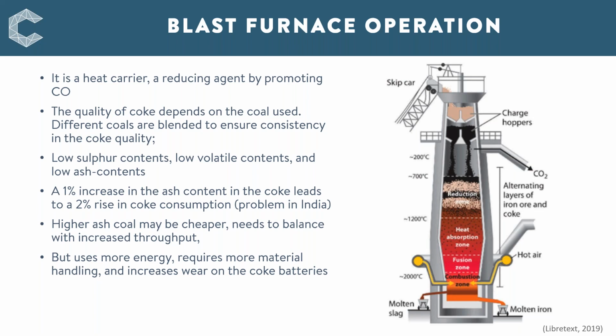Now that carbon monoxide then migrates upwards through the layers and the pores in these layer structures, forced by extremely strong currents of hot air from the tuyeres at the bottom. And this reduces the iron oxide in the upper layers of the furnace. In the middle, limestone decomposes and combines with silica and silicates in the iron ore to form slag, which is then tapped off to waste. The molten metallic iron or pig iron, along with the molten slag, then descend through the layers and are tapped at the bottom of the blast furnace.